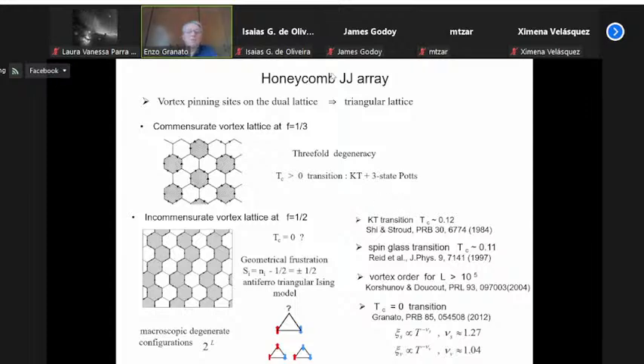For this case, the vortex pinning centers are at the centers of the plaquettes, the so-called dual lattice, from a triangular lattice. The nodes of these lines would be the locations of the grains, and the centers would be the centers of plaquettes, which form a triangular lattice. If the frustration is 1/3, with one vortex per 3 plaquettes, then there is a ground state that matches the pinning sites. In fact, this situation is 3-fold degenerate, and there is a transition at finite temperature.